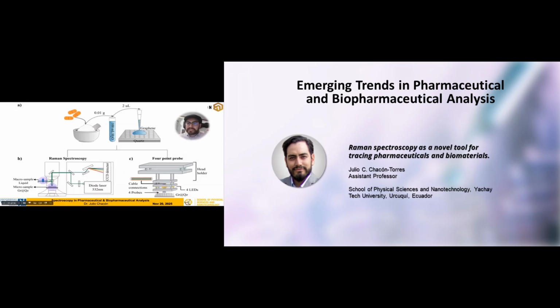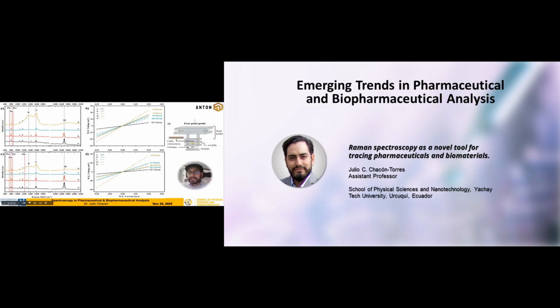Then we decided to study something else before we finished the experiment, and it's the conductance of this graphene. We know that the graphene conductivity is very important, and we wanted to know if it was affected by the presence of the molecule, and indeed it was. So we wanted to remove the pharmaceutical by heating the quartz plate, and then the graphene got oxidized. And now you see that the spectra doesn't look like graphene anymore. It looks more like a graphene oxide, still with some structure.